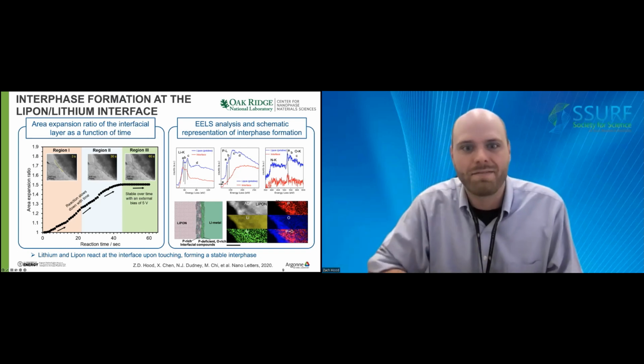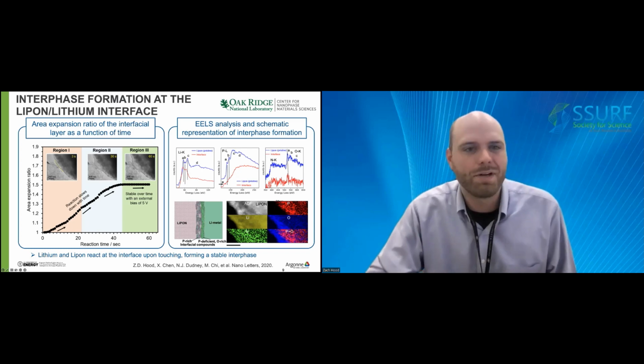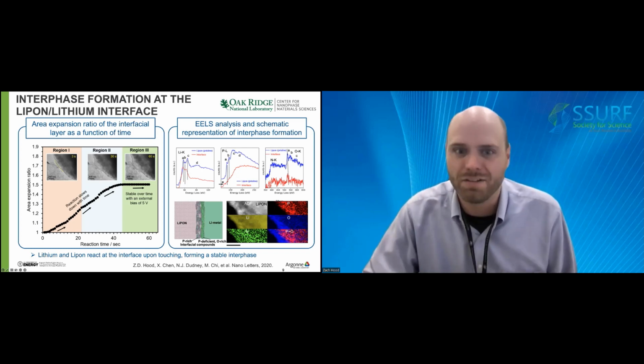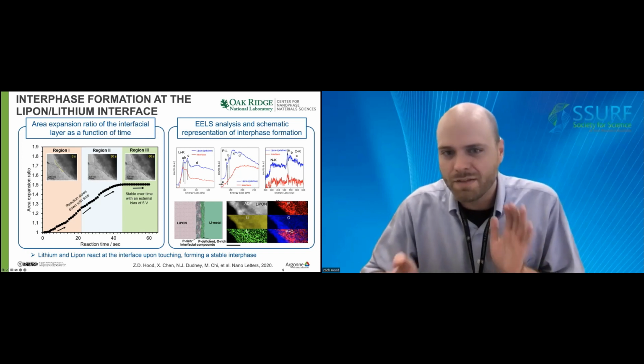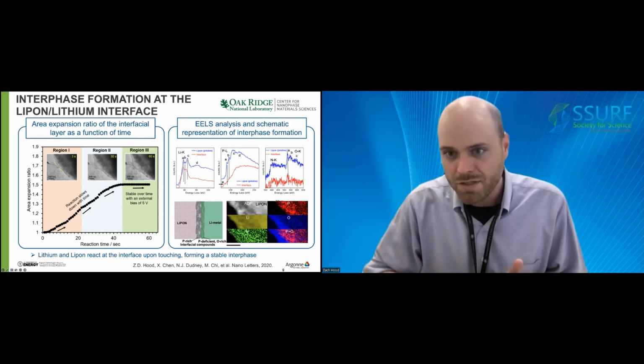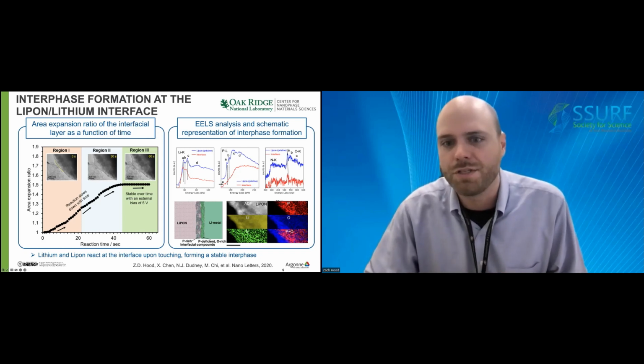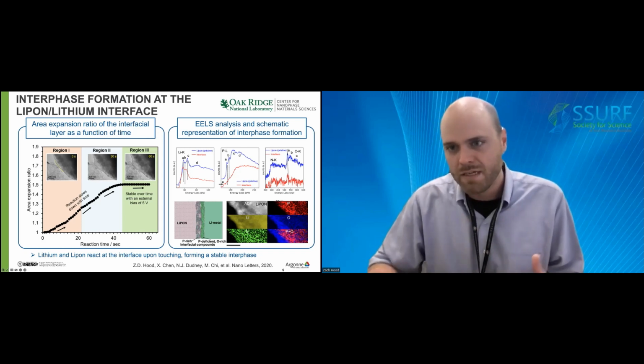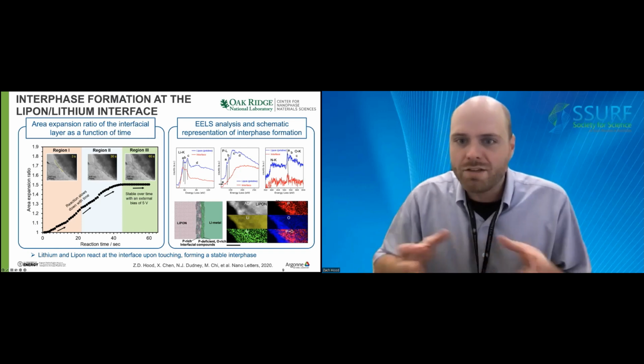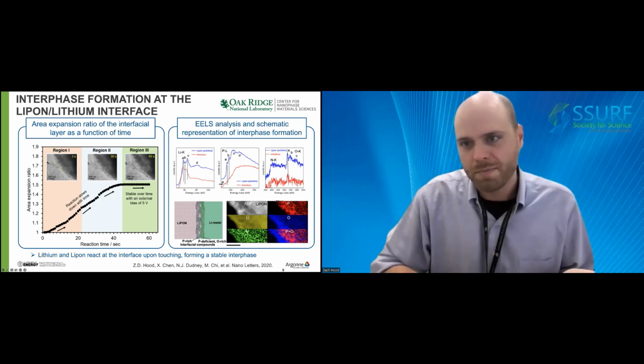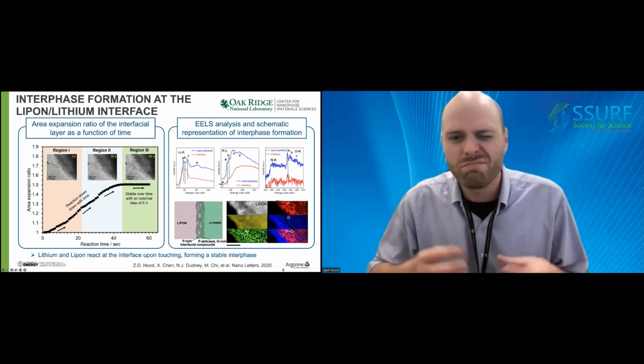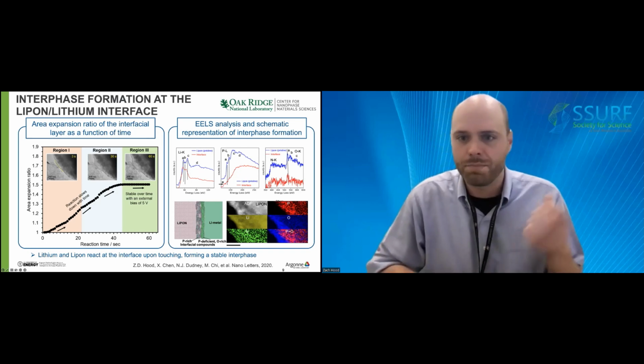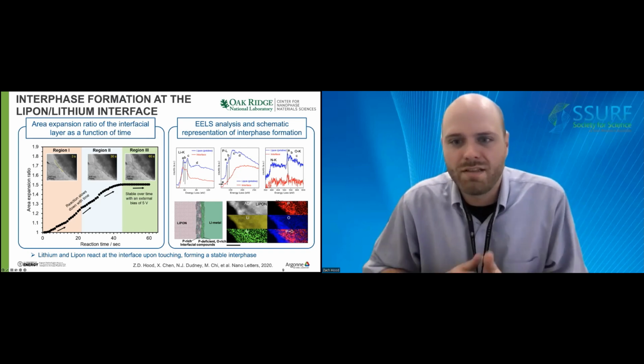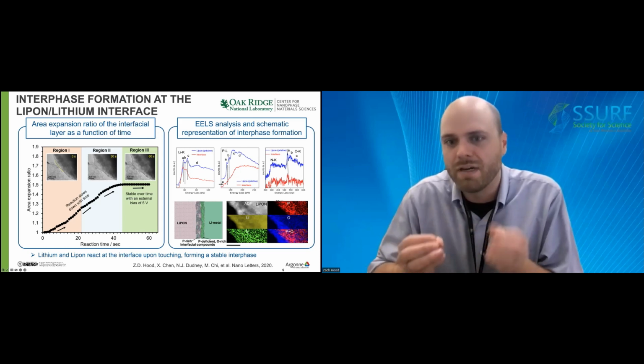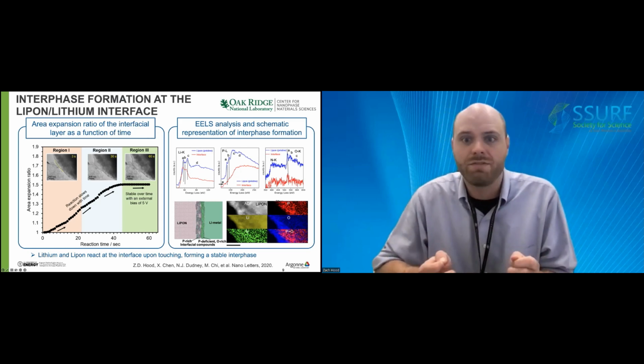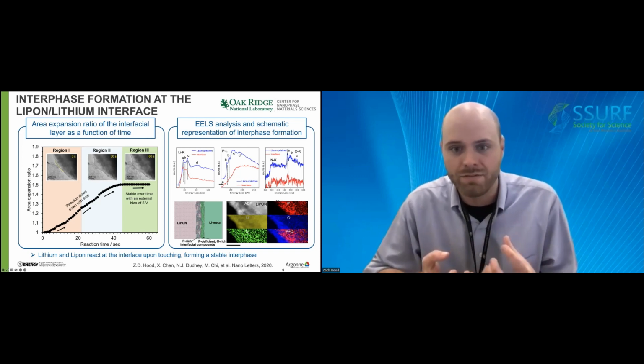The amount of energy loss can then be measured via an electron spectrometer and interpreted in terms of what caused that energy loss. So we looked specifically at the lithium, phosphorus, oxygen, and nitrogen regions of the material and saw some clear differences between the pristine solid-state electrolyte LiPON in comparison to the interface. Dramatic changes were observed in the lithium K-edge in the EELS spectra for the interfacial layer. Instead of multiple peaks observed in the lithium K-edge for the pristine LiPON, there were two main peaks in the lithium K-edge for that interfacial or interphase layer, implying that the lithium bonding configuration is significantly altered within the interface.